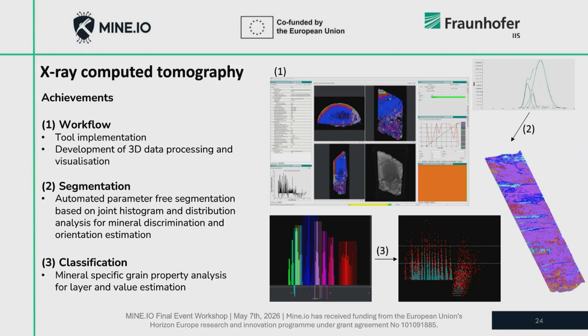Well, our workflow here was that we implemented a software tool that does the 3D data processing and segmentation. So the biggest challenge was to get started with the segmentation, and we developed a parameter-free segmentation tool that used the joint histogram method, so that we can get a start value for an estimation of the segmentation of the mineral groups, and we could use that then to refine it and put it into our deep learning models to do the actual image segmentation into these mineral groups.